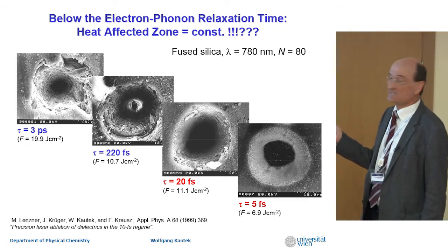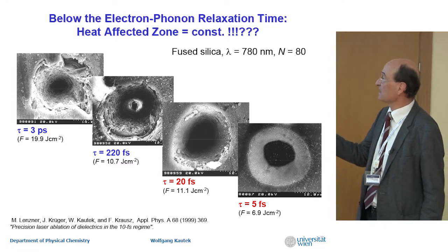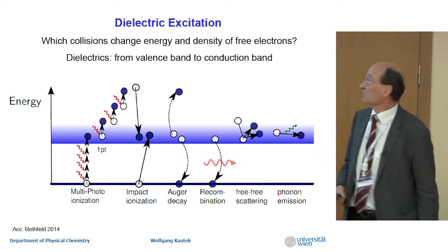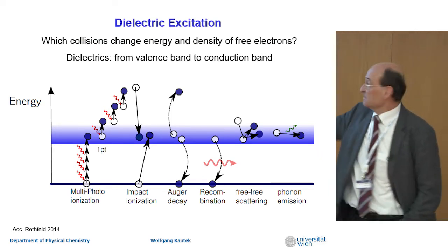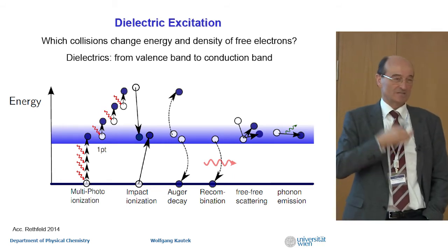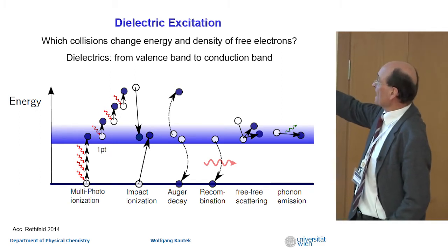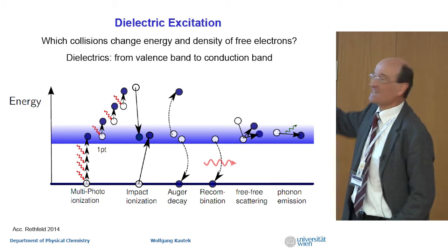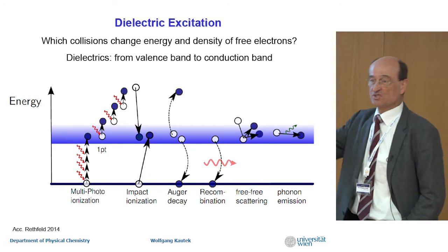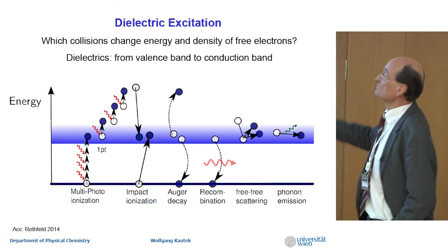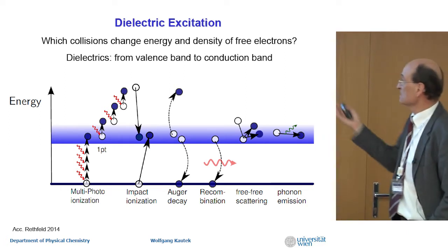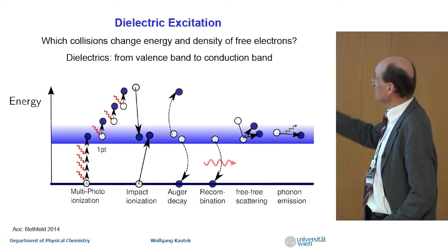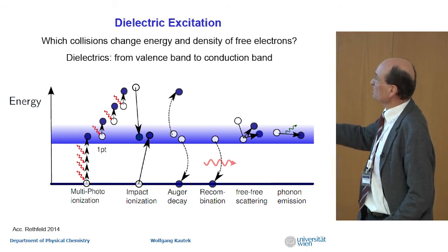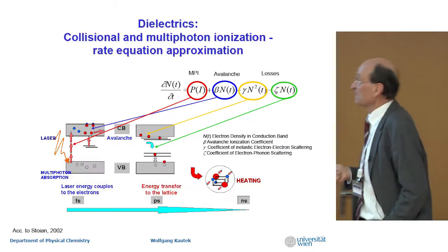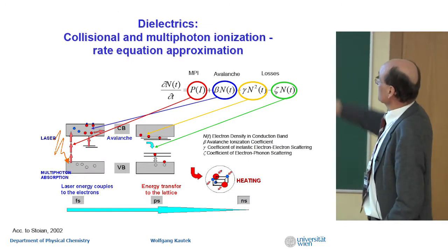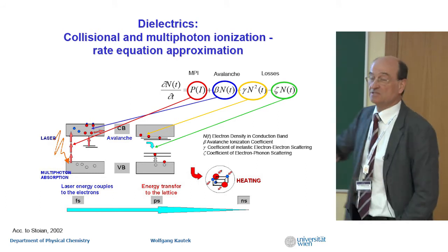Remember, we had these processes in the metal, just scattering of free electrons and then heat dissipation. Now, in dielectrics, it's more complicated. In dielectrics, we have the choice between a multi-photon excitation, otherwise we cannot couple light into it, or the impact ionization. Then we have the free carrier absorption, if we have free carriers, but we have to generate them first. Then we have Auger decay, we have the classical recombination, like you know from semiconductors, solar cells, and so on. And then you have the free-free scattering, and then the phonon emission. So, what process helps us to interact with the dielectric? Here, I would like to sum up with the help of Mr. Stoian in France. Here is the rate of generation of free electrons.